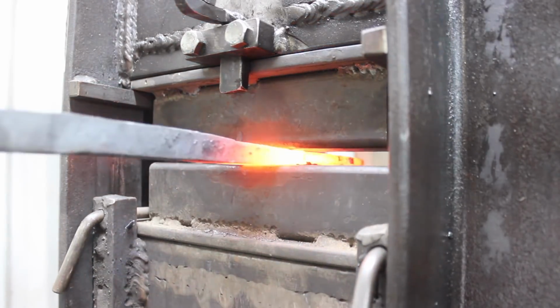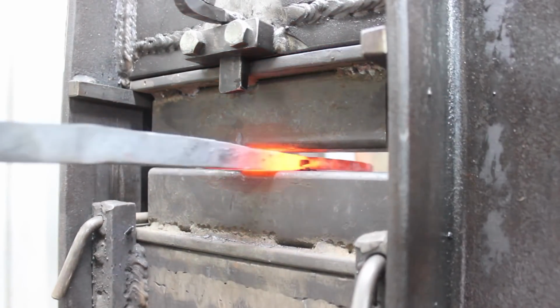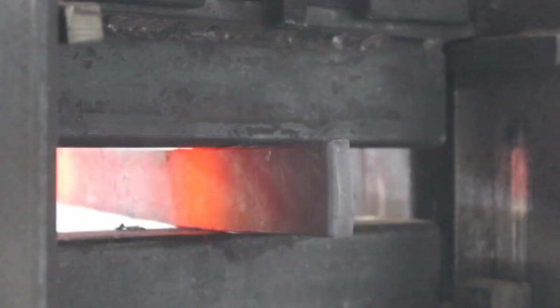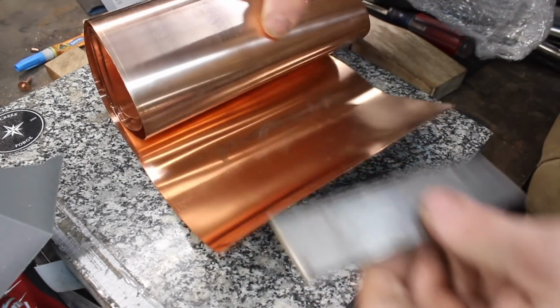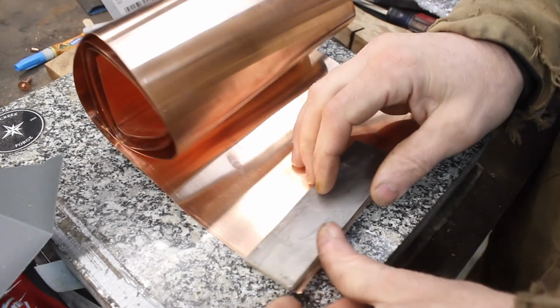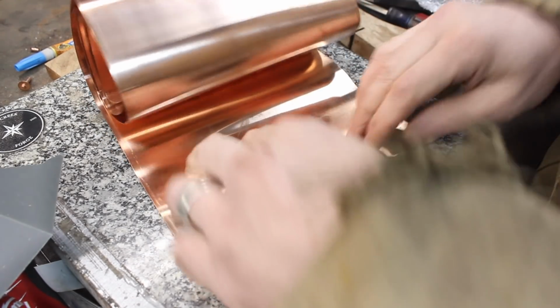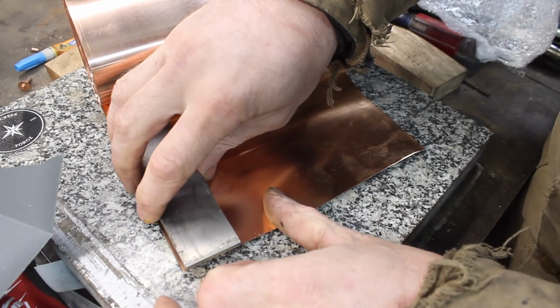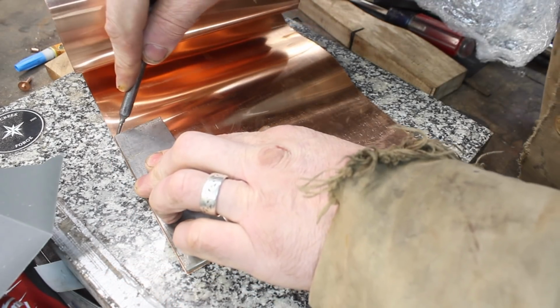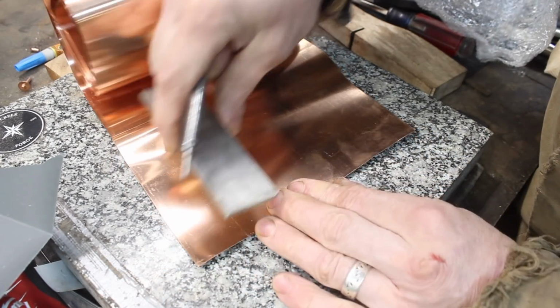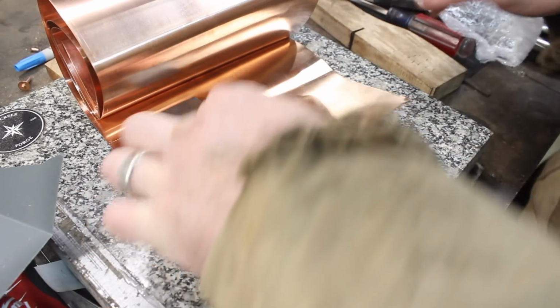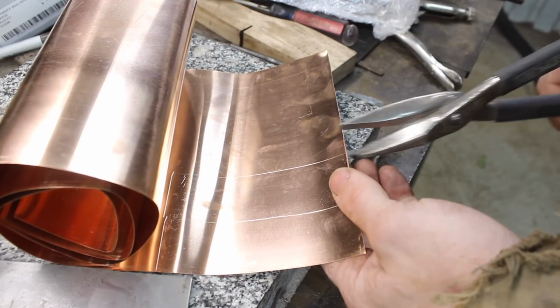What I'm doing here is drawing out pattern welded or Damascus steel that I've forge welded previously, and I need something that's about 1.5 inches wide and about 1/4 inch thick. So I've got my center piece of steel here, what's going to be the center piece in our billet for the edge steel, and this is 52-100. And then on top of that I've got some copper sheeting.